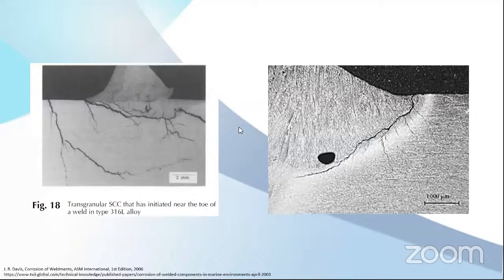You can see here this example of the stress corrosion cracking in 316L is almost always happen not in the weldment area, but in the base metal area. Because normally in the weldments, the stainless steel have some residual ferrite, delta ferrite. So sometimes the weldment area is more resistant to crack than the base metal area. This time is on the stress concentration area, it's on the toe. This is very high stress over here, so it can start cracking.